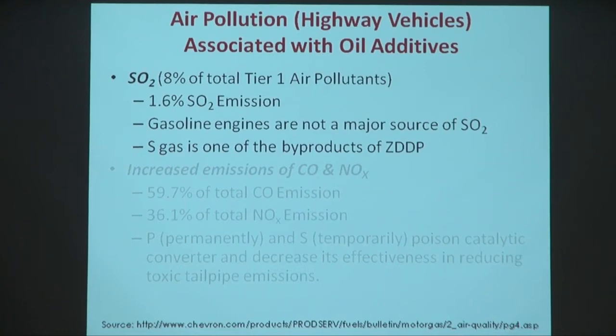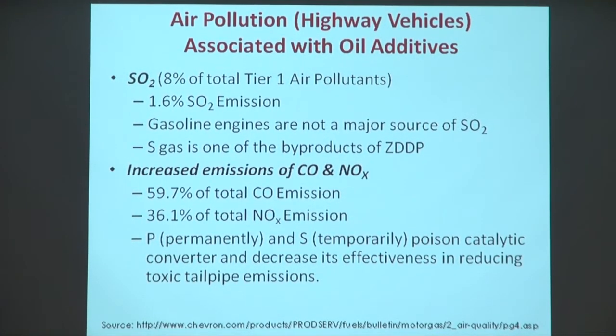But before I do that, let me add that the increase of these emissions of CO and NOx, in terms of some quantitative numbers that add up to these percentages, are an indirect effect of the presence of some elements like phosphorus and sulfur, which are main ingredients in additives used in synthetic oils for gear oils or engine oils to maintain their efficiency and optimum combustion process by reducing friction and wear between the various interfaces of these mechanical systems. But these additives, while effective in lubricating those components of vehicles, contain phosphorus and sulfur, which turn out to be poisoners of the catalytic converter.